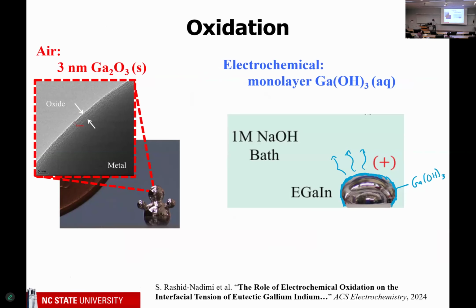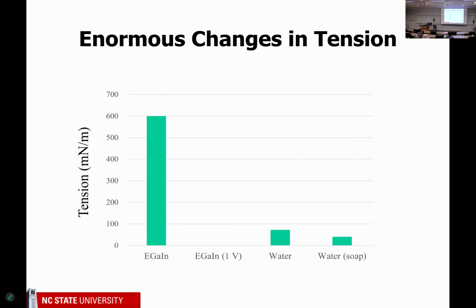And usually, well, okay, a couple things. So first, you might be thinking, wait a second. Didn't earlier he say that the oxide allows you to 3D print these kind of wacky shapes? Yes, that's Ga2O3, that's a solid oxide shell. But remember, we're doing these experiments in a bath that dissolves away the oxide constantly, so it actually allows it to flow. And not only that, we've now gone and measured, it forms a different type of oxide. So they're not exactly the same.